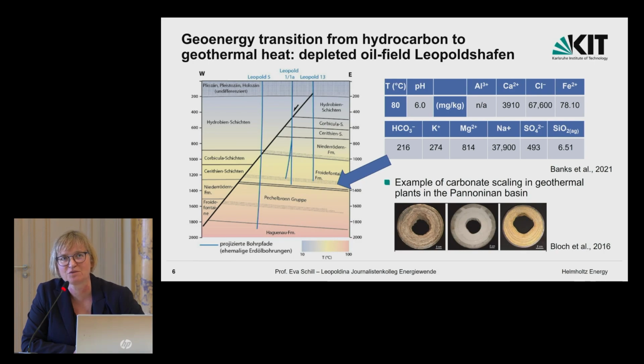What you see here is a section through a former oil field. It's a very classic oil field. You have gas on top, then you have the oil, and at the base you have water. The water in the reservoir has a very high salinity. You can see the values for chloride and sodium, I forgot. So it's about 120 grams of salt per liter of water. And you can see what the problem of this high salinity is in the lower part. This is from the Pannonian Basin. As soon as you change temperature, you have precipitation and you get scaling, and so the challenge is really to find conditions where we do not have these scalings.